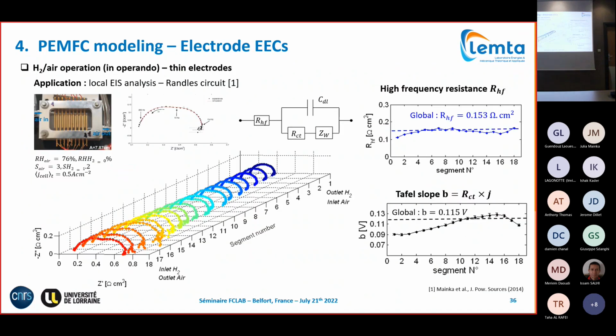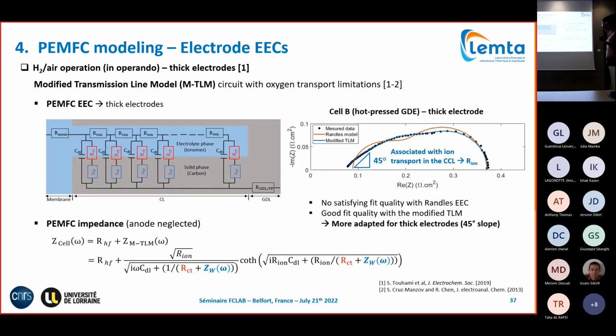So here, just as an application, what can you do with this? For example, you can fit your global spectrum with this Randles circuit. You can analyze your local spectra that you measure with this cell locally, from the inlet of your air along the flow until the outlet, and identify here your high frequency resistance, associated with membrane ion conduction, and do this also along your fuel cell, compare to the global spectrum, and go into more detailed interpretation to say what you can do in analyzing your electrokinetics.